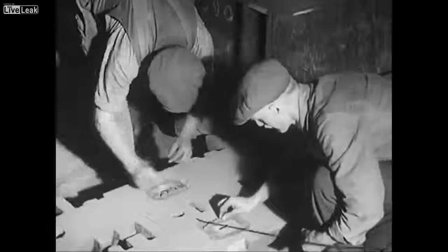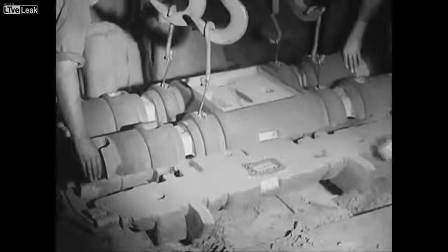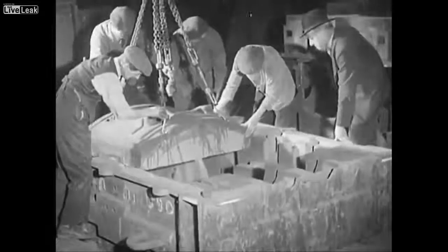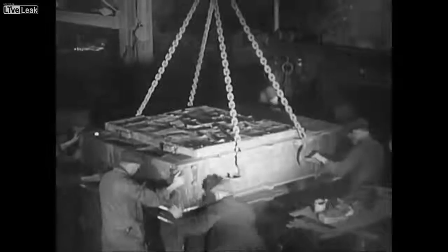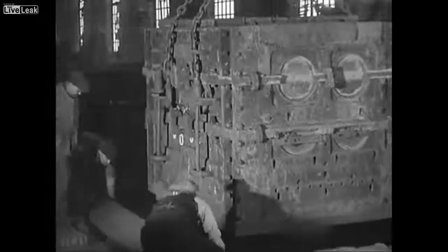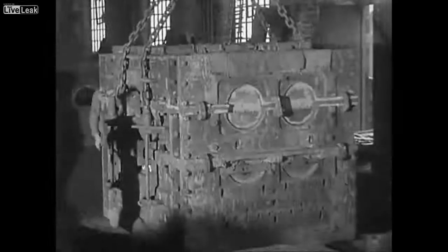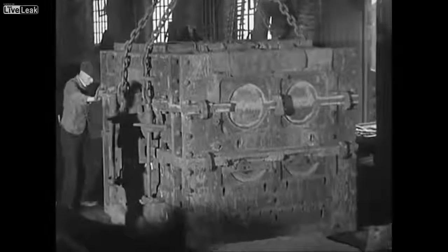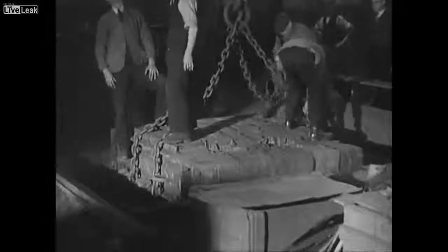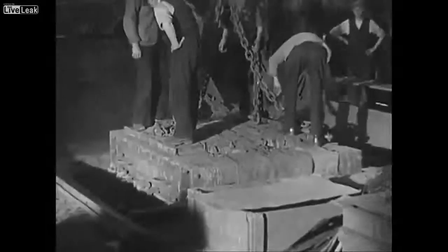Foundry work is rather paradoxical. It is what isn't there that matters. A mould eventually consists of an ordered assembly of spaces into which the molten metal is poured. Over 60 moulds and cores are required to make a pair of inside cylinders for our engine. Skilled workmen fashion them in sand from patterns made of wood. The assembly of the cores in a mould is a task something like fitting together a giant jigsaw puzzle. A 12 hours drying causes the sand to assume a consistency which enables it to withstand the great pressure of metal soon to be placed upon it.